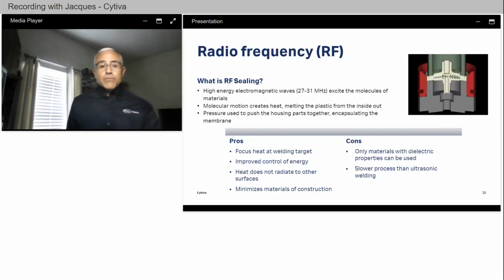The advantages of RF welding include the ability to focus the heat at the welding target so that the surrounding material is not exposed to high heat, therefore reducing the risk of burning the material. In second place, heat is generated only when the field is energized. This allows for greater control over the amount of energy that the filter membrane and housing sees over the entire cycle. One other aspect is that the heat from the RF process does not radiate off the plates like other heated surfaces, like the first method we had discussed. This prevents heat degradation of the filter material bordering the seal area.